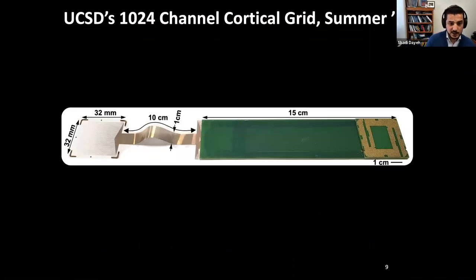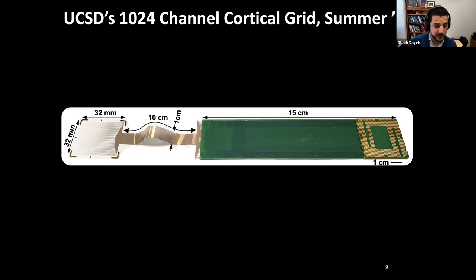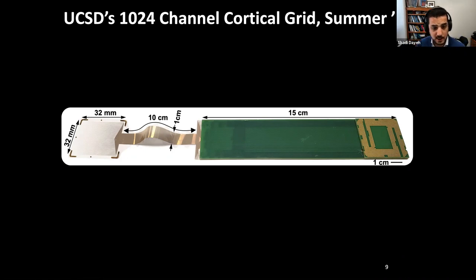So at UCSD, what we've done over the last few years is developed a grid on Parylene C substrates. These substrates are 10 micrometers thick or less. So they are very thin, they can be conformal to the surface of the brain. And over the years we have scaled the number of channels to currently 1024 that's used in the operating room. This is manufactured on large substrates so that we can separate the surgical medium from the non-sterile medium where we will have the electronics to acquire these signals.